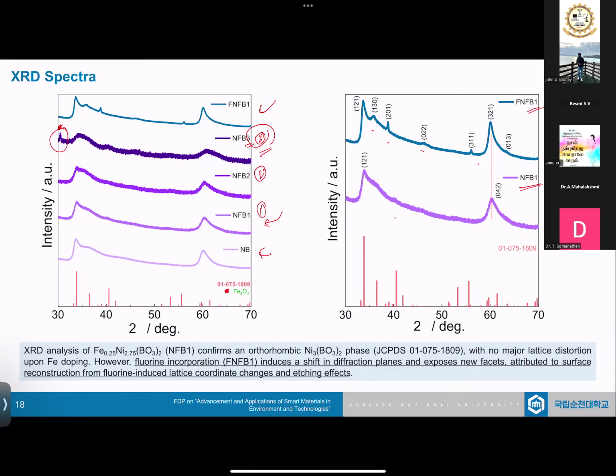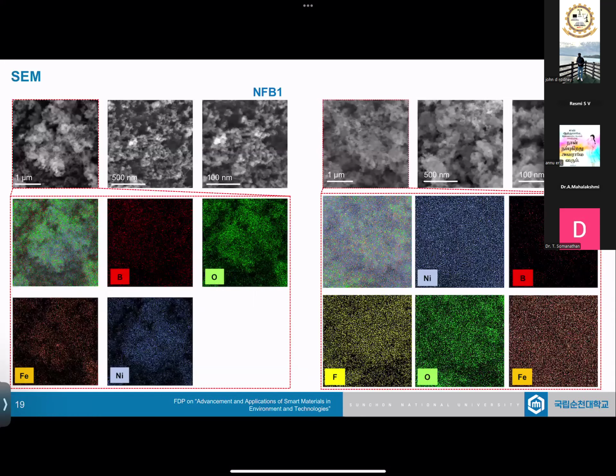So again, we are going into the exploratory research where we are moving further, checking the usual stuff that everybody does, that we move into SEM and we see that the morphology doesn't change much because we know that it won't change because we are trying to just replace some atoms, not extensively, in a very small manner. And also we are bringing in fluorine in a very small manner so that the surface might be etched slightly, and when compared to the shapes that have been present, we can see that's a very, very slight change in morphology.